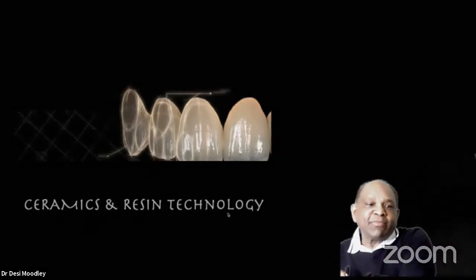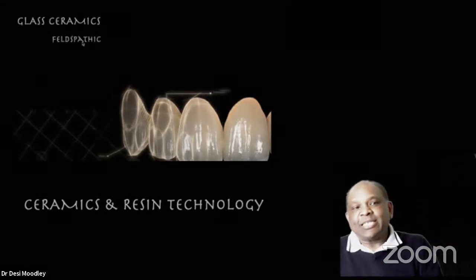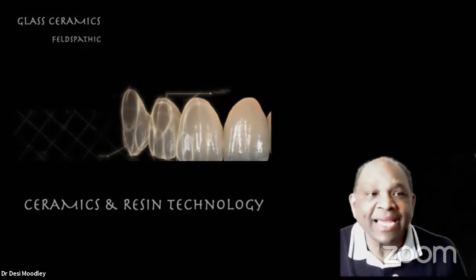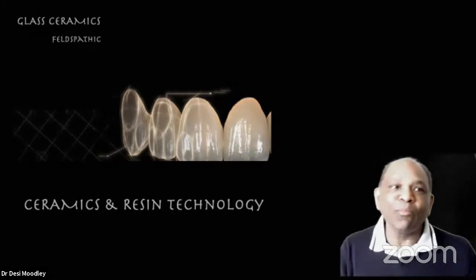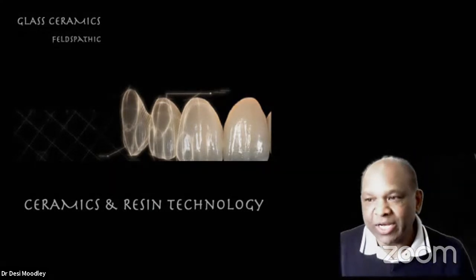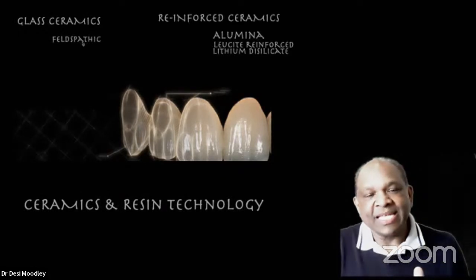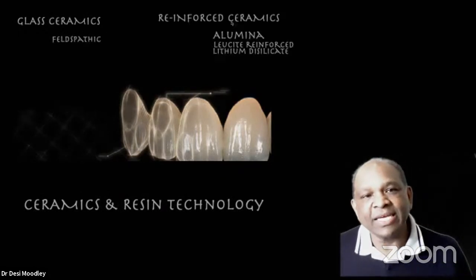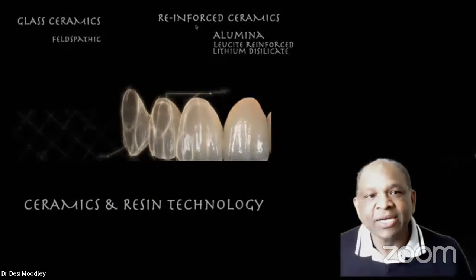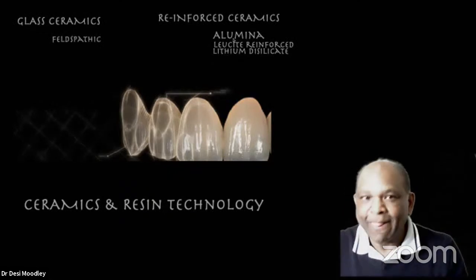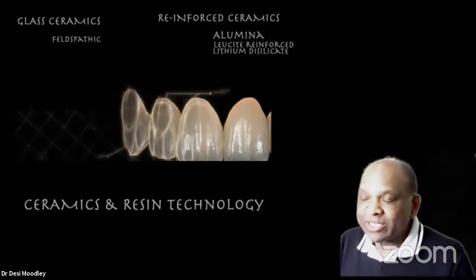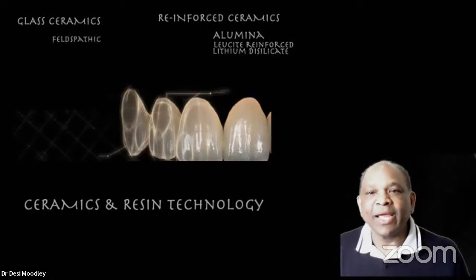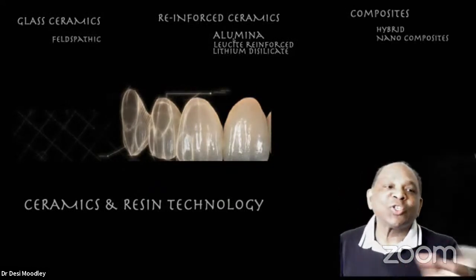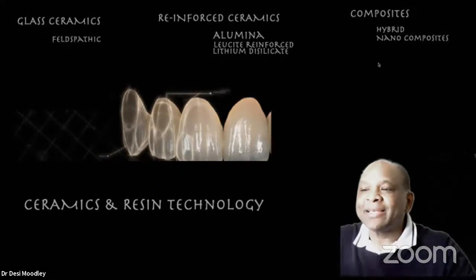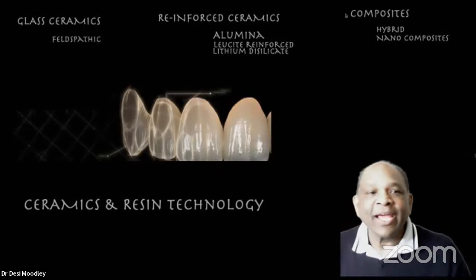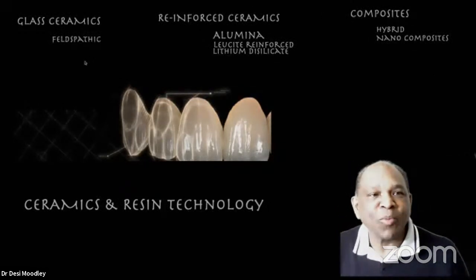So if you look at the spectrum of materials, we have glass ceramics on one side. That is mainly a feldspathic. This had the best aesthetics. But the problem with this material was it wasn't strong enough. So what they've done is they've reinforced this glass ceramics with alumina or lithium disilicate to get the reinforced ceramics. So then the strength increased. But with that, this material was still a bit brittle, so it would crack and chip. Okay, and then of course, composites on the other end was not strong enough and didn't have the aesthetics of this, but it had a little bit of resilience and you could repair it. So ideally it would be to have a material that can incorporate all three of these properties.